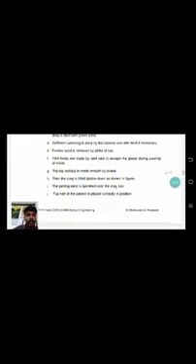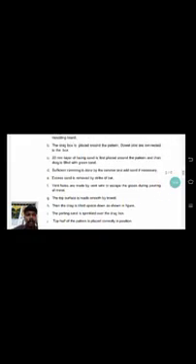Vent holes are made with a vent wire to let gases escape during the pouring of metal. Then in the next step, the top surface is made smooth by trowel. Then the drag is turned over. Parting sand is sprinkled over the drag box. The top half of the pattern is placed correctly in position. These are the procedures to follow in the casting process to manufacture whatever product we require.